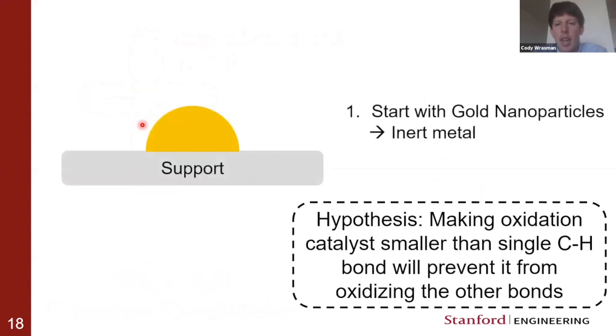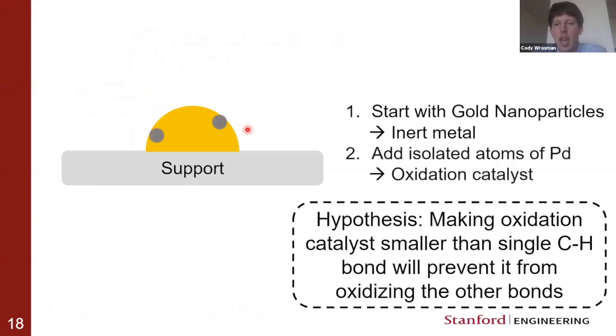So the way we did that is we took gold nanoparticles, which are inert for any of these oxidizing reactions, and we took palladium, a metal that's very, very good at these CH bond oxidation reactions, and we wanted to add the palladium in single atoms or isolated atoms of palladium inside of gold. So in these catalysts, the gold is really just being used as a holder to stabilize these single atoms of palladium that we hope will only be able to access one of those CH bonds.